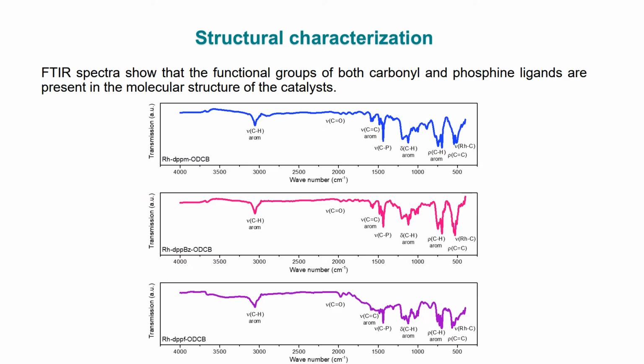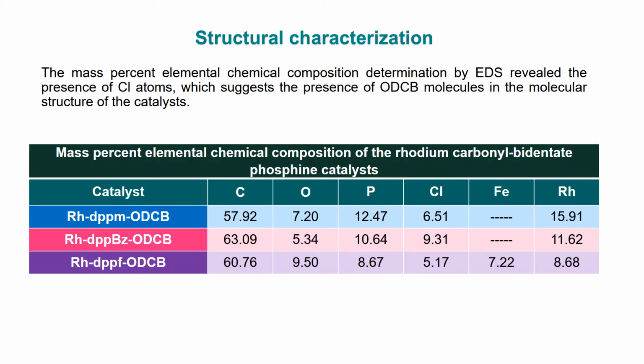Fourier transform infrared spectroscopy spectra show that the functional groups of both carbonyl and phosphine ligands are present in the molecular structure of the catalysts. The mass percent elemental chemical composition determination by energy dispersive X-ray spectroscopy revealed the presence of chlorine atoms, which suggests the presence of ortho-dichlorobenzene molecules in the molecular structure of the catalysts.